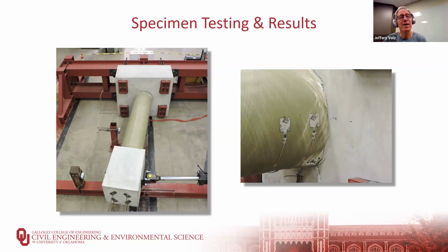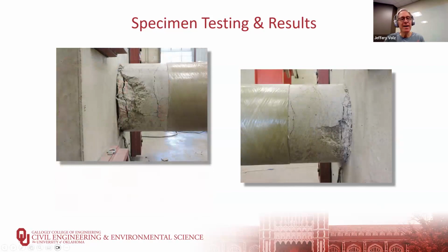At the bottom of it, where the FRP comes in contact with the concrete base, you see some white there. If you see a close-up on the right, you can see that this white is where the FRP has started to split. And here it's actually fractured. These are the strain gauges measuring the hoop strain in the FRP during testing. And here, the compression has gotten so high on the concrete that we've exceeded that 40 KSI hoop stress for the FRP. We then circumferentially cut the FRP and then slice it longitudinally to peel it off and to look at the concrete underneath.